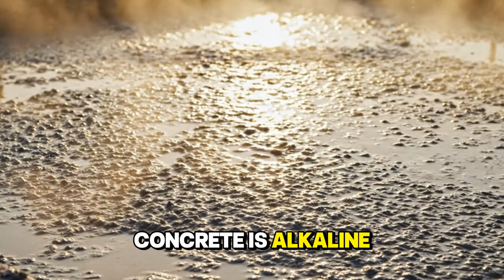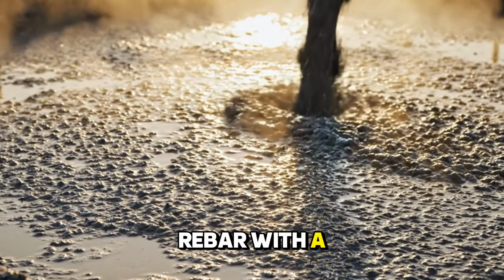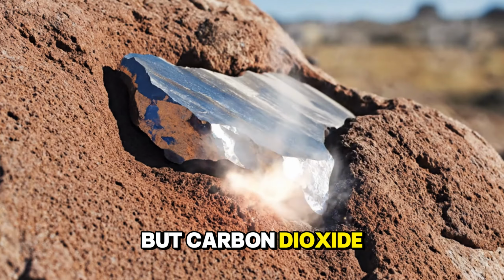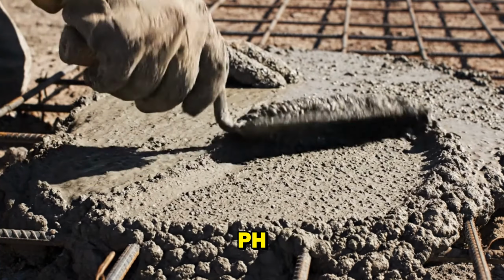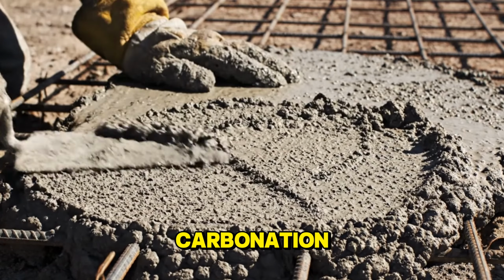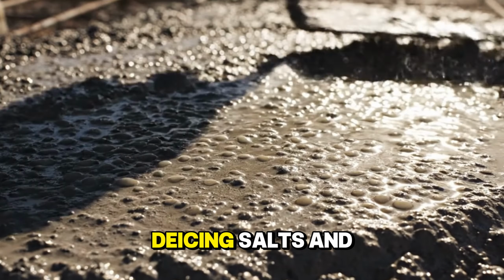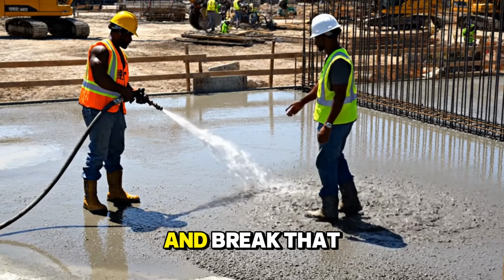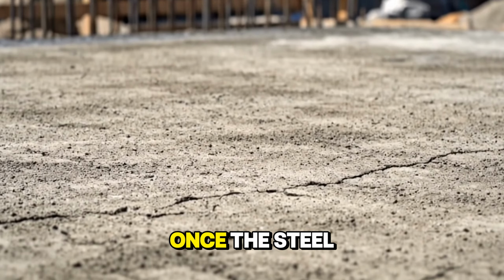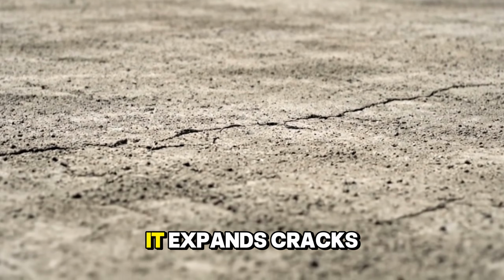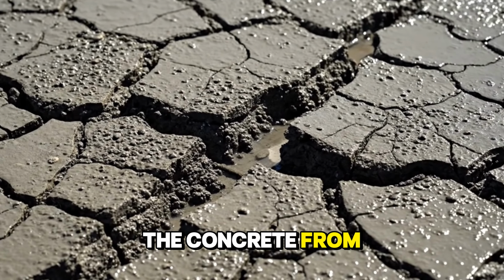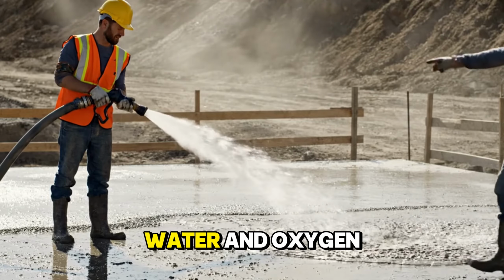Concrete is alkaline, which protects the rebar with a passive film. But carbon dioxide from the air slowly lowers the pH, a process called carbonation. Chloride ions from deicing salts and seawater sneak in and break that protective film. Once the steel starts to rust, it expands, cracks the concrete from the inside, and invites more water and oxygen